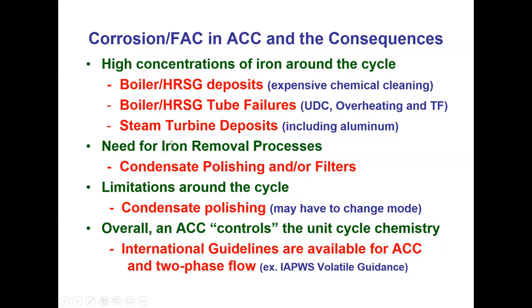And there are also, over the years, we've seen steam turbine deposits, and particularly with regards to the aluminium from the ACC. We need to have iron removal processes, condensate polishing or filters. There could be limitations then when we have to control the FAC. We might have to change the mode of operation of polishers. And overall, what we find is that if there's an ACC in a particular plant, then it basically controls the unit cycle chemistry. There are, of course, international guidelines that are available for ACC and for two-phase flow.